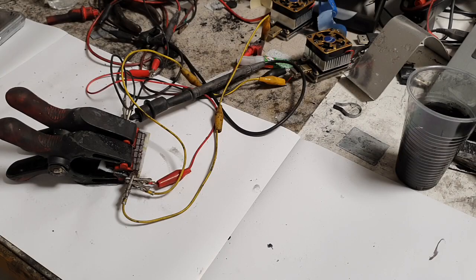The lead acid battery has lead oxide for the positive active material, which is put on a lead grid. The lead grid is the current collector, and the negative electrode is made from lead powder, also put on a lead grid. Then we also have a separator and the electrolyte. The electrolyte is sulfuric acid, and that's it. This is the design of a lead acid battery.